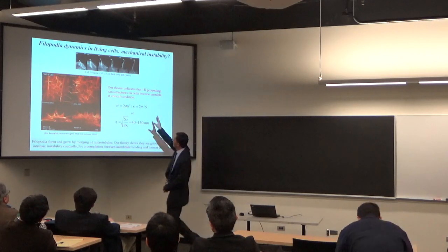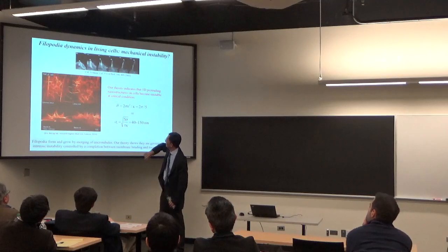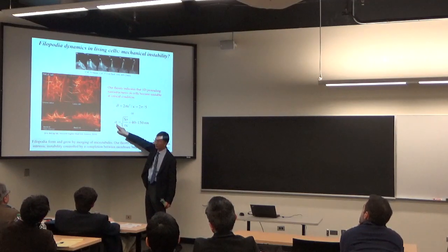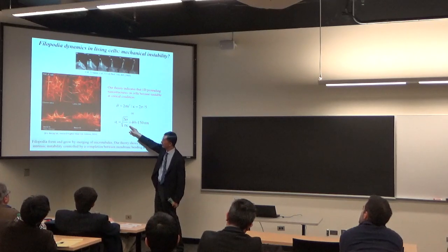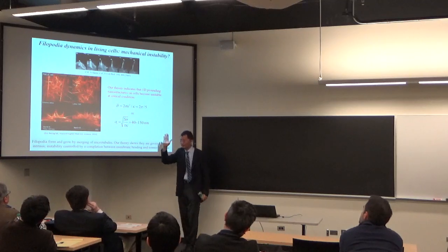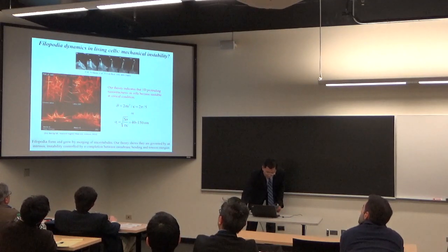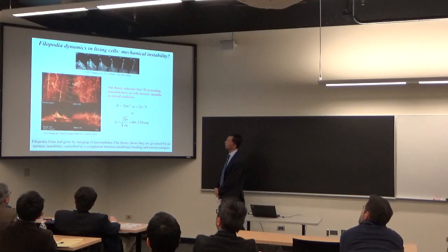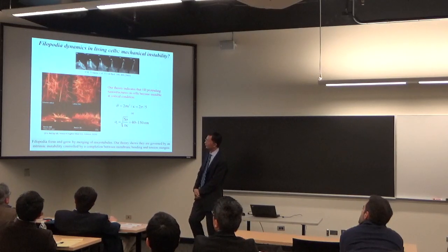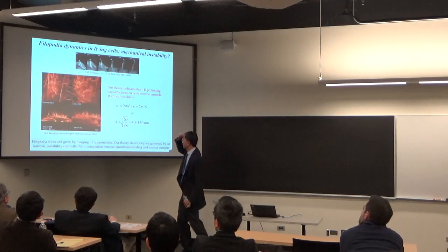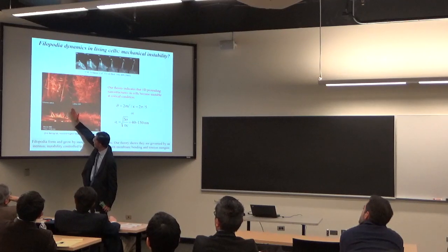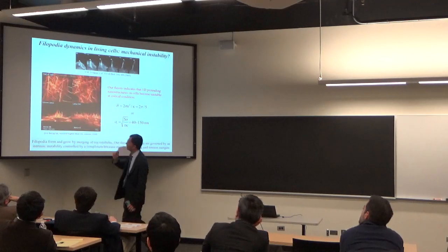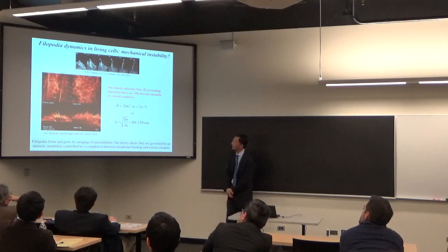Again, our theory, where we write down the free energy, would predict that when the filopodia grows to a critical diameter, about 40, depending on cell type, and it varies, then the filopodia should first stand up, then lie down, right? So when we look at this movie again, this movie was only possible with a new bioimaging technique from only a couple of years ago. We can see that these filopodia all undergo some mechanical instability. They lie down. Initially they stand up on the cell membrane, and at a critical diameter they lie down.